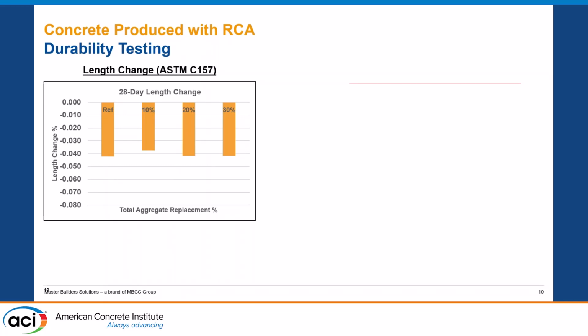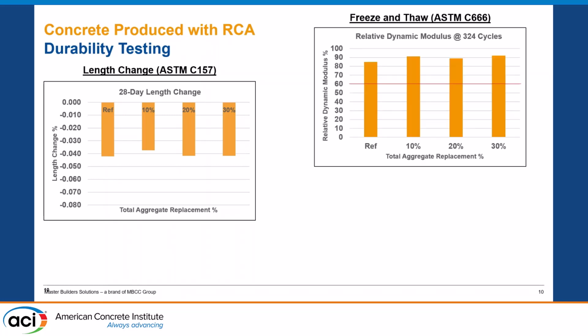Compiling all the data from the different mix designs, what we can see is that in terms of length change, when tested according to ASTM C157, length change is also very comparable. The concrete behaves basically the same. In terms of freeze and thaw durability, when tested according to ASTM C666, in this case method A, the relative dynamic modulus also does not vary. Very comparable results.